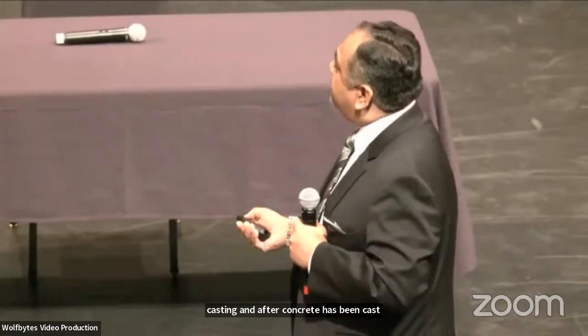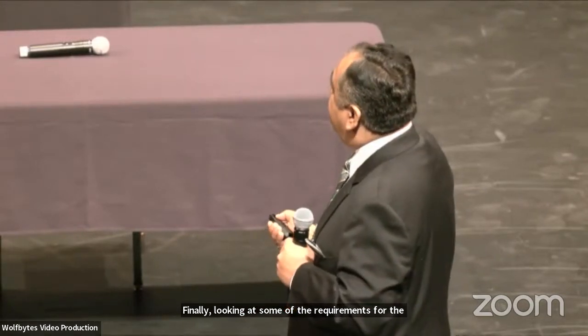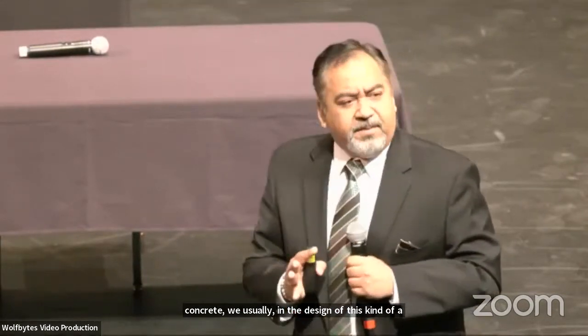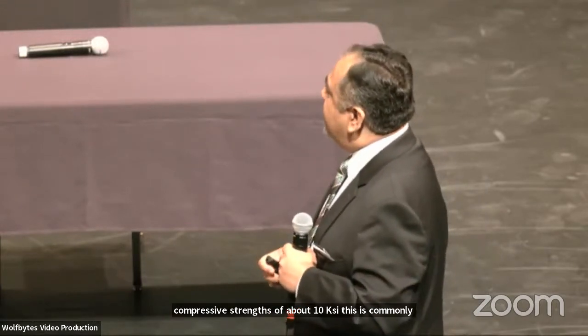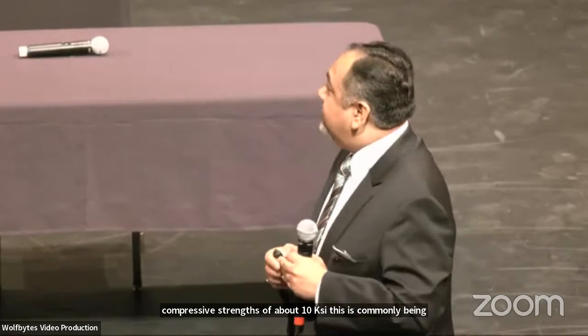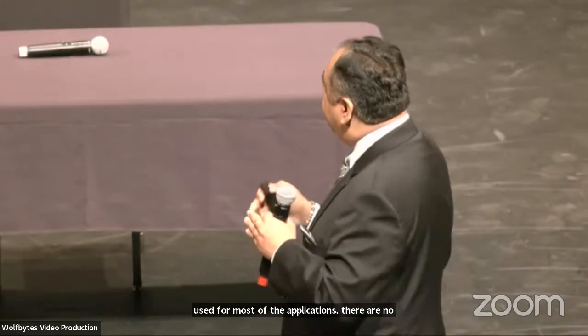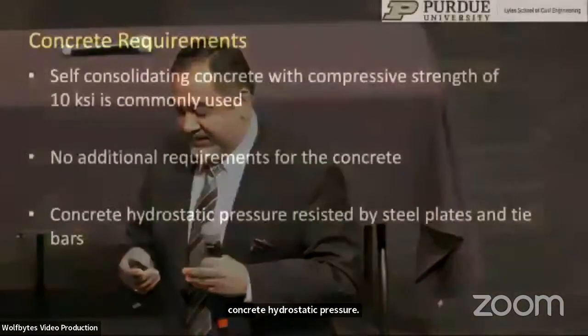Finally, looking at some of the requirements for the concrete, we usually, in the design of this kind of a speed core system, use self-consolidating concrete with compressive strengths of about 10 KSI. This is commonly being used for most of the applications. There are no additional requirements for the concrete, and the concrete hydrostatic pressure when the concrete is cast is resisted by the steel plates and the tie bars.